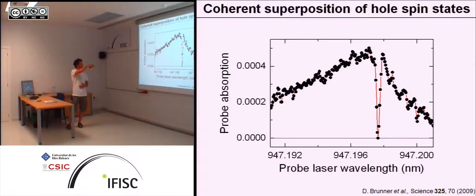And in the middle, or almost the middle, we suddenly see this very dramatic and very, very narrow dip all the way down to 0. And that is exactly this quantum interference between hole spin up and hole spin down state, which in this case is dark. So the two really important messages to take away just from this graph, without doing any further analysis, is that the dip is all the way down to 0.